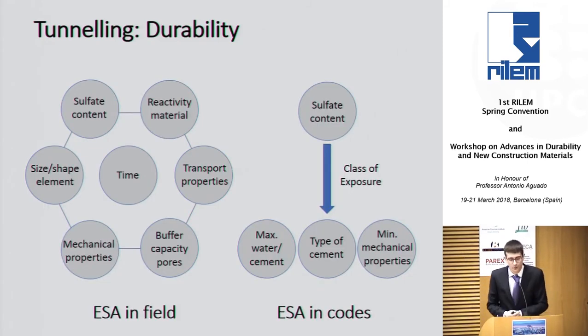So the traditional view for protecting our tunnels against sulfate attack, external sulfate attack, was based on the use of a sulfate-resistant cement. So you specify a sulfate-resistant cement, right? We have to check if this is applicable for sprayed concrete also, because when you spray in a tunnel, you usually add an accelerator, right? And the accelerator might have aluminates in the composition. So the use of a sulfate-resistant cement might not be enough to prevent the degradation of our concrete.